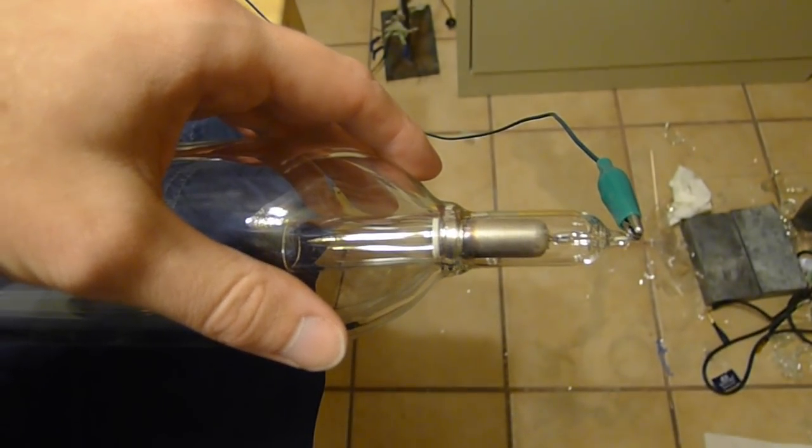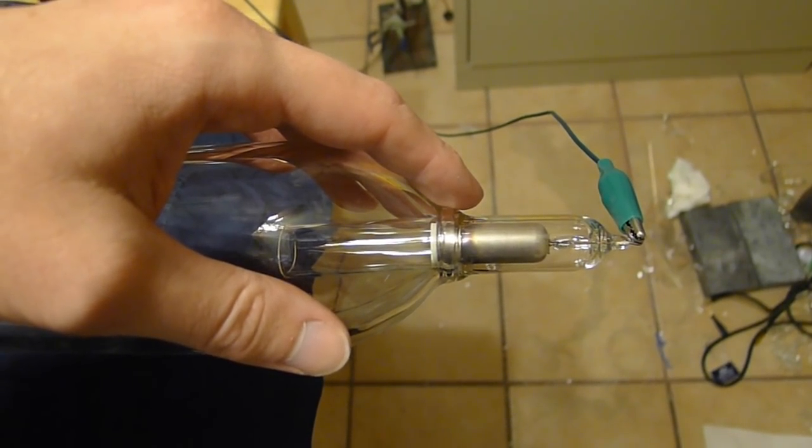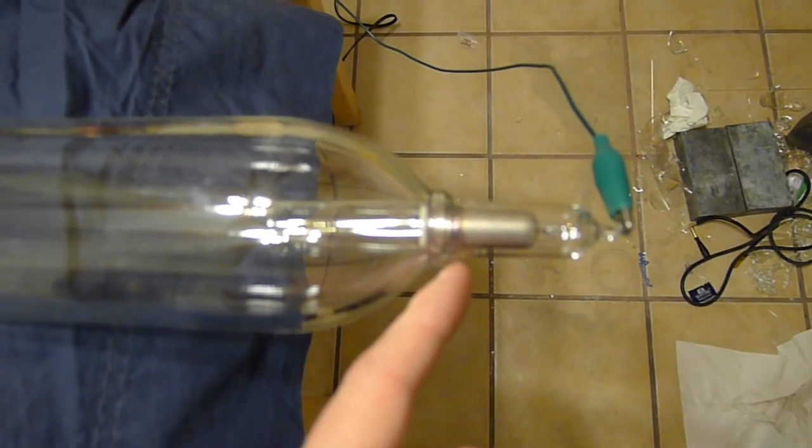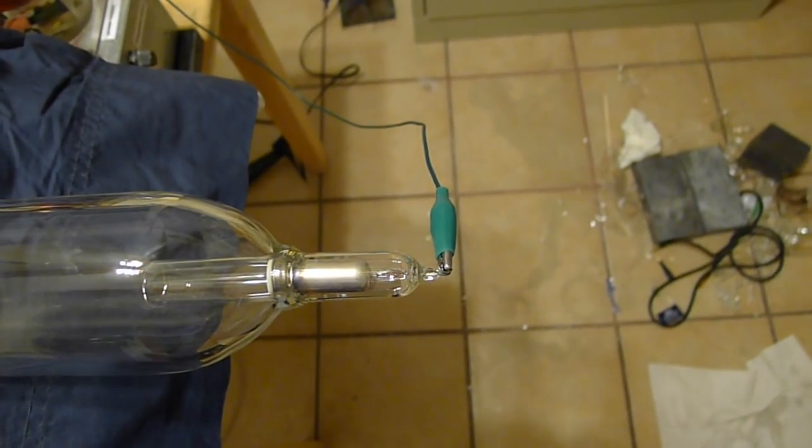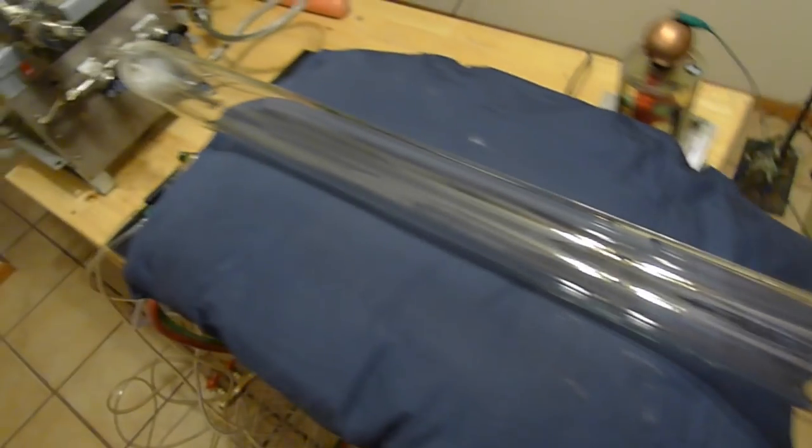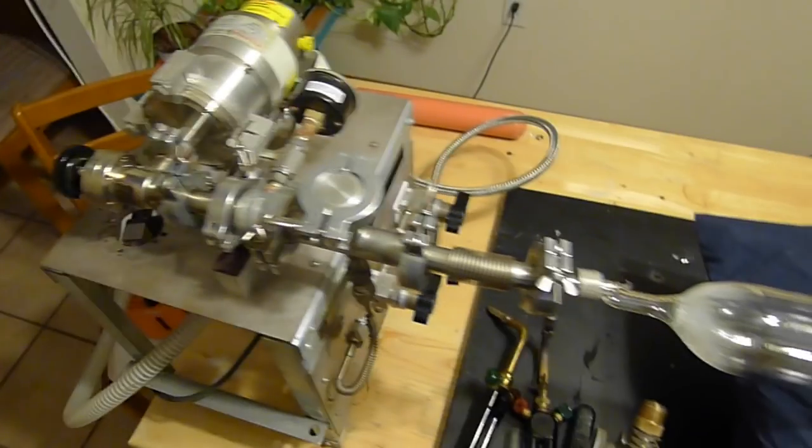Over on this side we have a typical neon electrode. This is a borosilicate glass commercial neon electrode. These cost about $10 a piece. I have done nothing to the electrode other than blow out a ring in the middle of it and then the seal here is known as a ring seal. We puff up the glass a little bit and put this in here all under constant rotation and just fuse that electrode in there. This type of seal you want to anneal very carefully because it's prone to cooling down faster in some places and cracking.